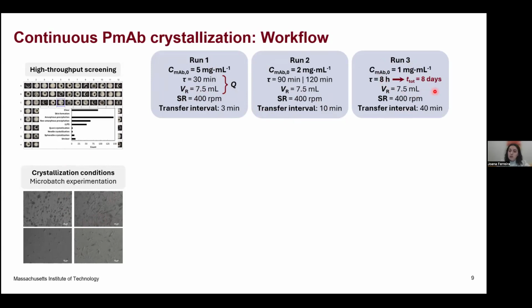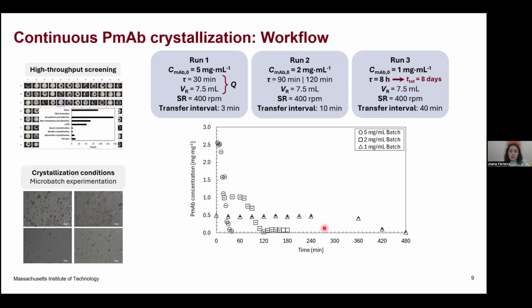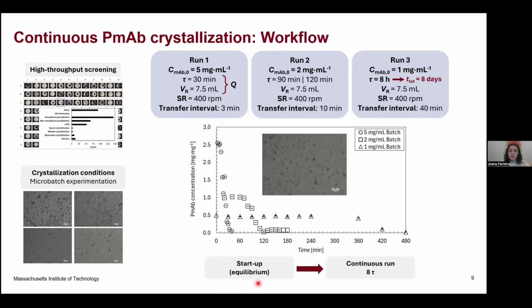And here what was very interesting is that for the third and last run, we were able to run it for more than a week, 8 days. This is something very, very long, and it hasn't been reported for proteins. In this graph, I'm showing the decrease in the concentration over time for the batch process. We have this startup, or we can call it equilibrium step, where we just run a batch process. We obtain the first seeds, and then we start pumping. So we are running our continuous process, and we do so for 8 residence times. Here you can see the decrease in the concentration for the 3 different runs. And what is interesting to see is the different time frame if you compare 5 and 1.